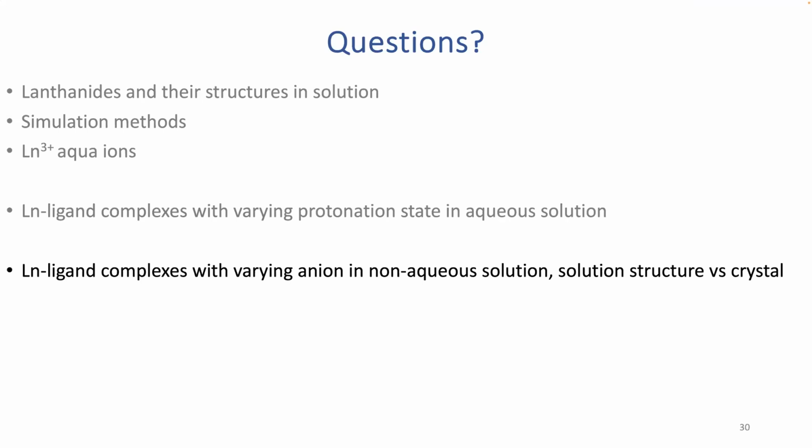It's just a comment. I just wanted to point out that in this particular case, in my experience, the asymmetry in the oxygen first shell is not coming from actual dynamics, but from static asymmetry in the distances of the oxygens. There are like 6 of them, or 8, I can't remember. They all have slightly different distances, and that makes the asymmetry. So it's pretty much non-dynamic. It's fairly static.